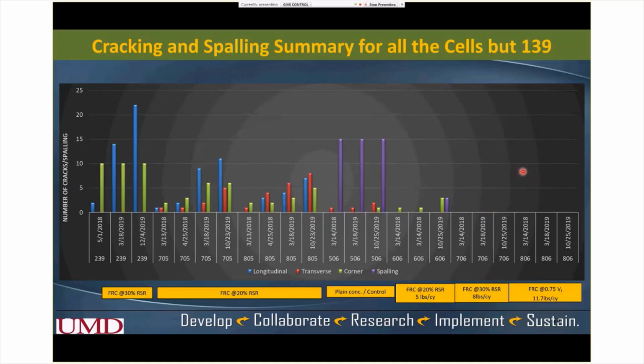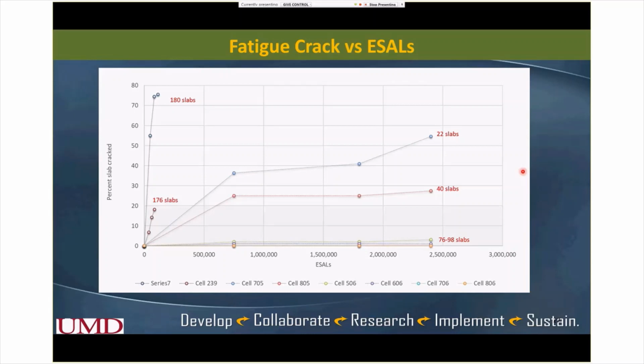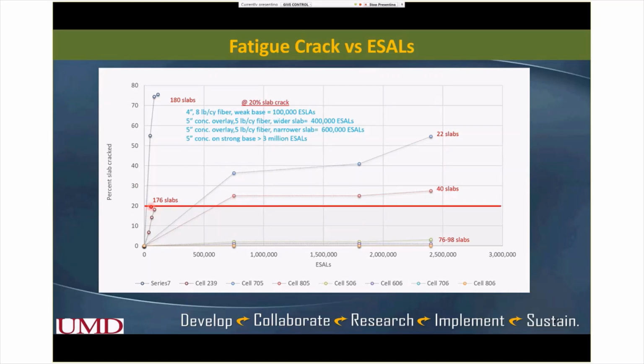Now this slide shows the percent slab cracked versus ESALs, and these are for all the 8 cells. You can see here, if we consider 20% slab cracked as the design life or fatigue failure criterion, cell 239 is pretty close, and the two unbonded concrete overlays have already crossed, and the 4 others, which were constructed on a thicker base, are still performing well in terms of cracking. So these are some numbers I just came up with.